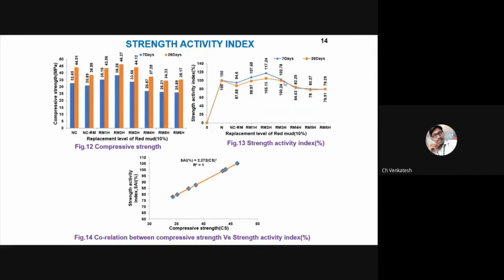Then I randomly replaced 10% of the cement, and I evaluated the compressive strength of all the calcined red mud samples. The 2 hour sample obtained the maximum strength. In the microstructure analysis also, we have shown that at 2 hours calcination time, the red mud particles are poorly crystallized. That's why we got maximum strength here.